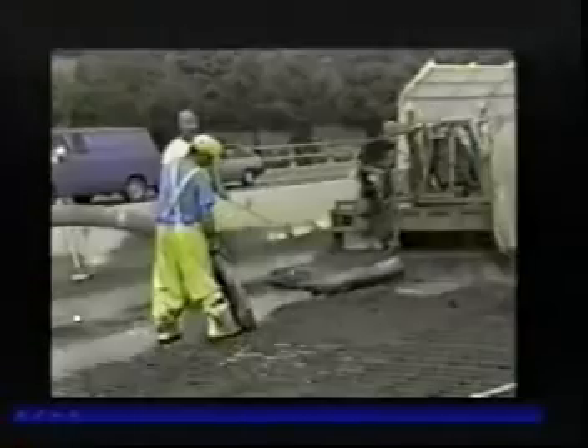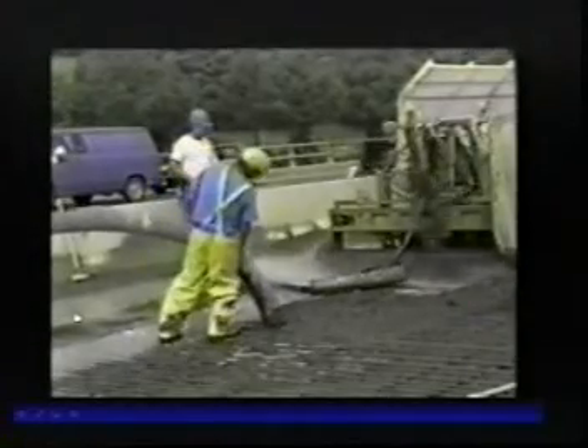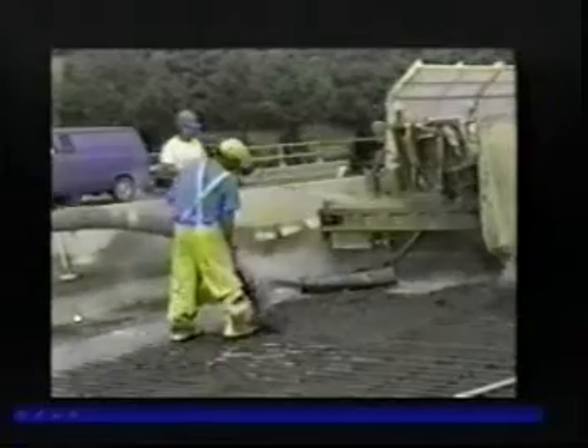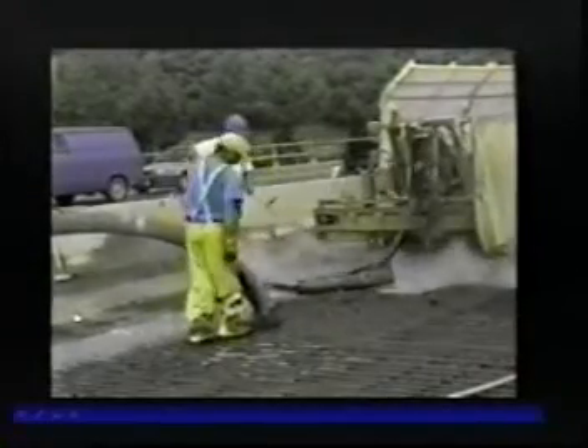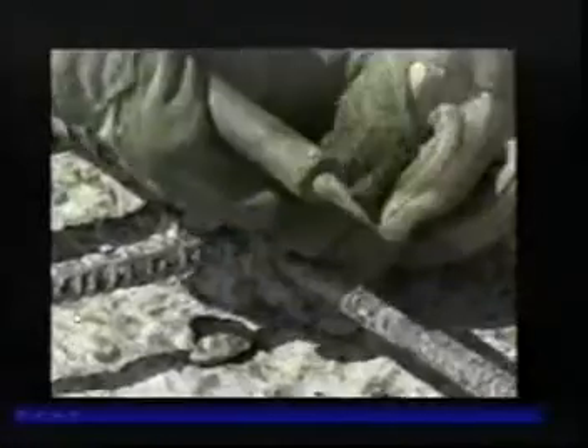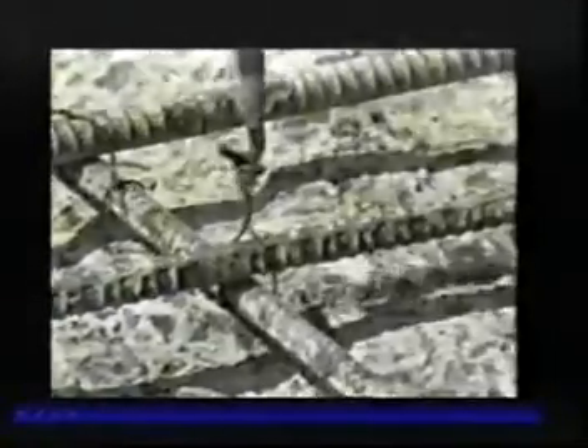Preferred method is abrasive blasting over hydro pressure, as you can see here. And this is a removal of the slurry from the hydro demolition process to make sure we get it down to clean, sound concrete. But this is typically, again, used for horizontal repairs. Any loose steel that's encountered in the repair needs to be retied. Many times when you're doing the demolition process and preparation process, some of the bars become loose. It's very important to retie those, as you can see here.